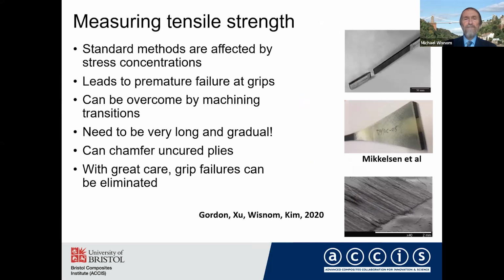So let's just talk about measuring tensile strength. It's about the simplest thing you could want to do, but it turns out to be actually quite difficult. The problem is that the carbon epoxy is so strong that it fails where you grip it. Standard methods are affected by the stress concentrations, and that usually leads to premature failure. Now, you can overcome that by machining very gradual transitions, but generally you need to have very large radii, very gradual transitions, and the specimens need to be very long with a gradual transition.